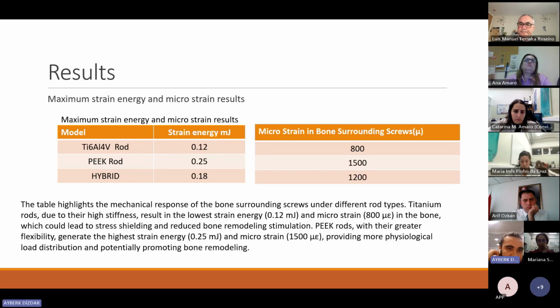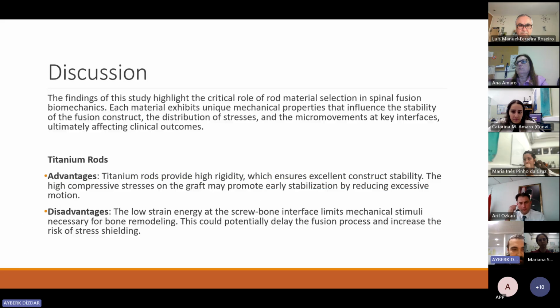Also, we obtained maximum strain energy and microstrain results. It's very important for bone remodeling. The table highlights the mechanical response of the bone surrounding screws under different rod types. Titanium rods, due to their high stiffness, result in low strain energy and microstrain in the bone, which could lead to stress shielding and reduced bone remodeling stimulation. PEEK rods, with their greater flexibility, generate higher strain energy and microstrain, providing more physiological load distribution and potentially promoting bone remodeling.